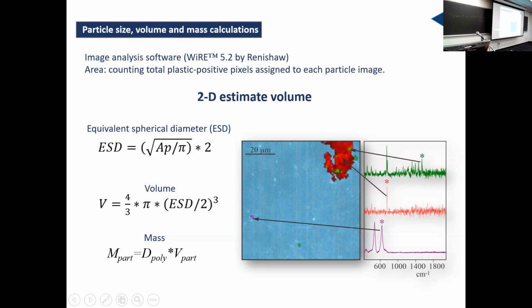You said that some particles came from a recycling process because they had combinations. Can you speak to what proportion of particles exhibit this recycling characteristic versus just pure plastic? Yeah, we found a lot of these mixed particles. When I say mixed particles, it's different polymers in the same particle, polypropylene and polyethylene mixed together. I would say it's like 2 or 3% in every sample, in comparison with pure plastic. And the pigment that I mentioned is everywhere.